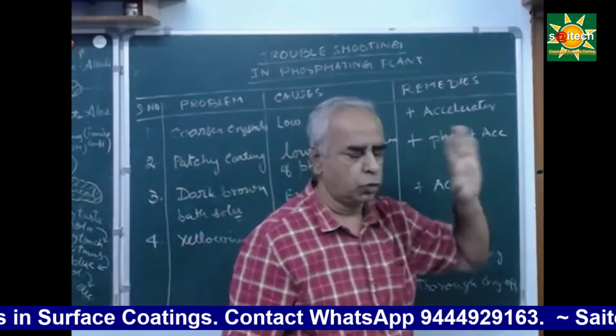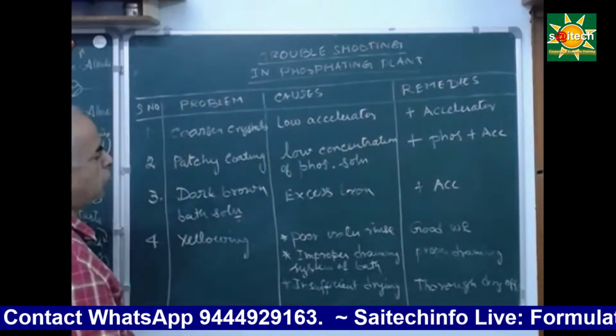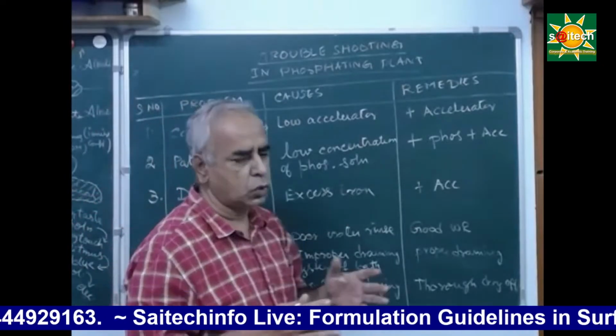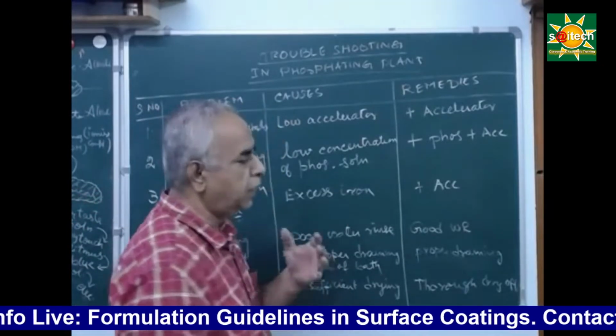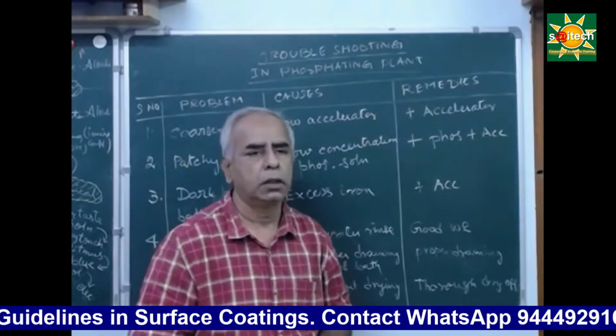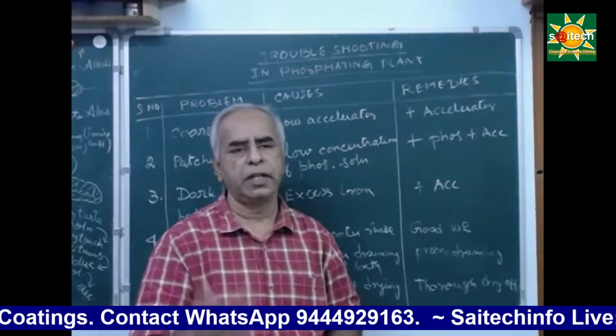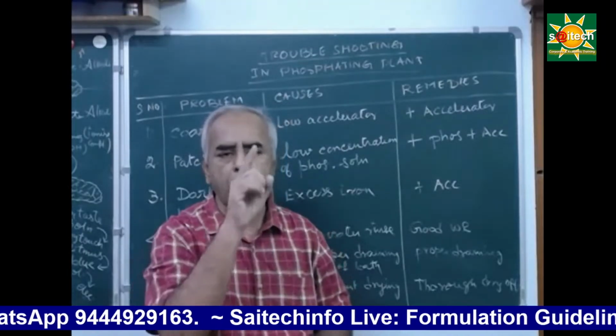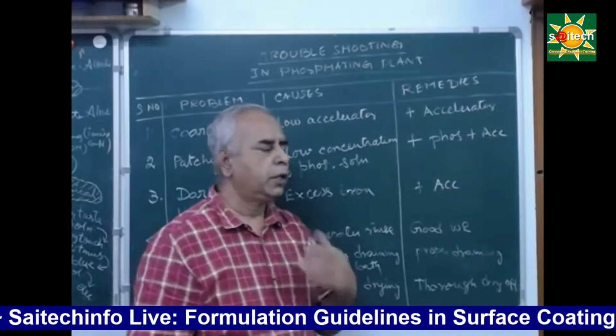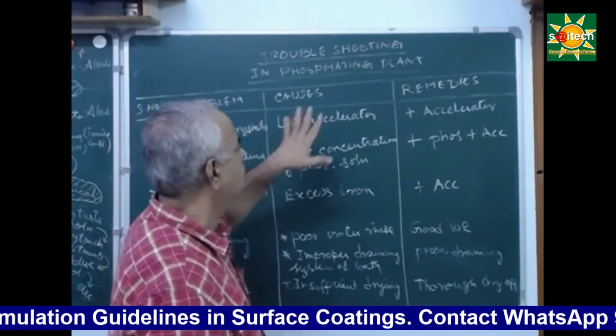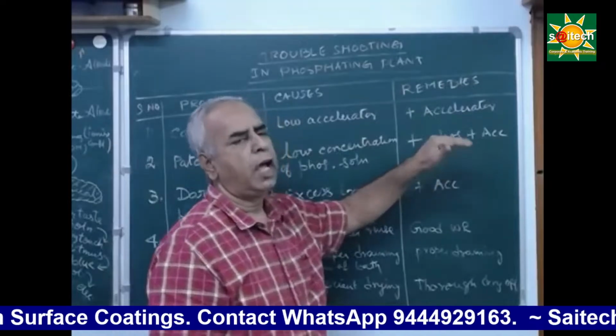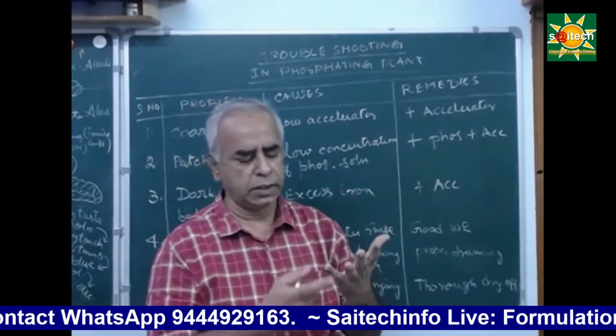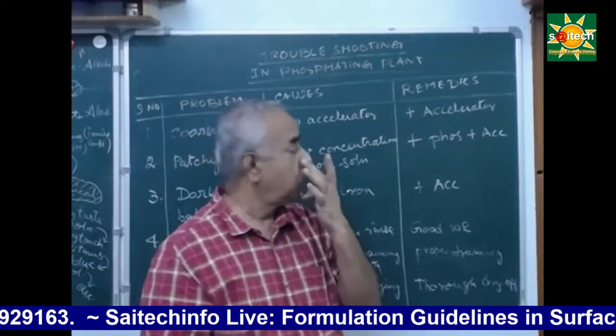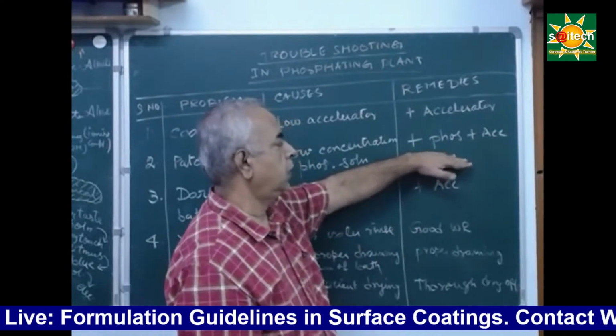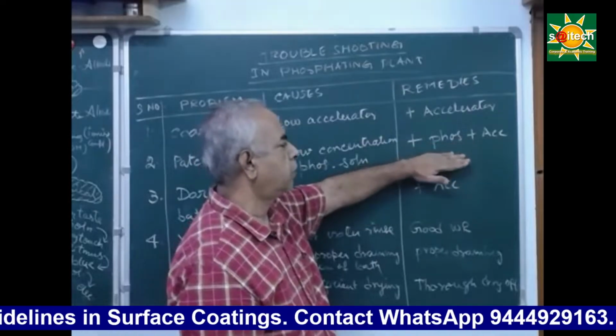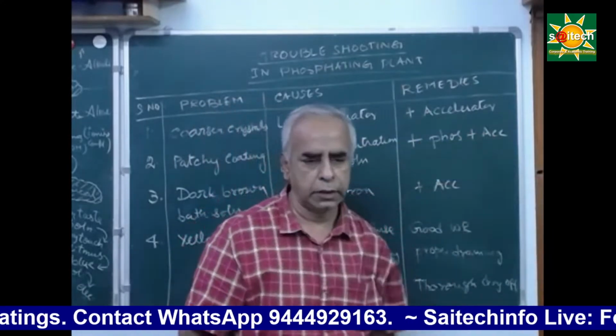Is it okay? Right. And then patchy coating. Sir, there are some patches, it is not uniform. So in that case, it indicates that your bath concentration, its total acidity, free acidity, everything has been affected. So you have to take care of the bath parameters, and you have to top up with the zinc phosphate solution. Actually, it is available in various ways, as a single pack or dual pack, etc. So you have to add it necessarily in the given ratio. So you have to add phosphate. Along with that, you have to add accelerator also.